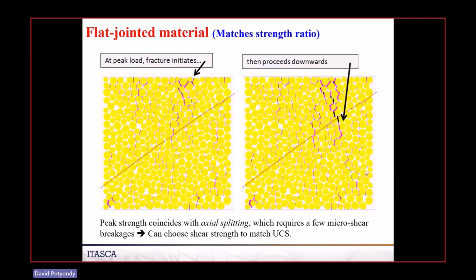If you look in detail at this, this is what's happening right at the peak load. You're basically getting a localization to happen here, and then it's proceeding downward to break the system. Again, the black color is micro shear failure. So in order for this to localize and create that axial split, there has to be some micro shear failure. So that's the key thing that's allowing this to reach the peak, to begin to fail. So it's that micro shear strength that can be chosen to match the UCS.